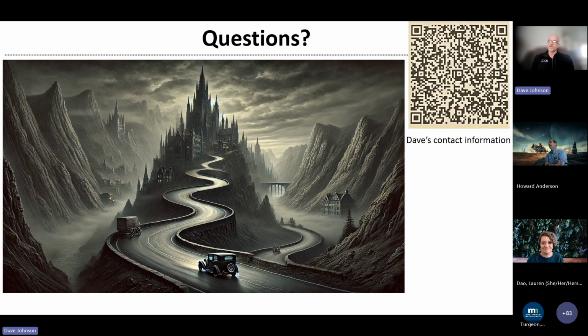All right, and I appreciate those comments, and we do have some questions in the chat. We have a question about the Hamburg wheel tracking temperature. What's your opinion about the temperature, a constant 50 degrees C regardless of the PG grade? In our western states, historically, we have had adjustments. So Colorado, Utah, and Montana have all adjusted their Hamburg temperatures relative to the high PG grading. There's different ways that states approach that, and we could have a significant conversation around temperatures. Some states keep that constant temperature, but will make adjustments to the wheel passes, excuse me. Others will make adjustments to those temperatures, and there's some other approaches that people take. Arguments for and against different temperatures and different passes could be made.